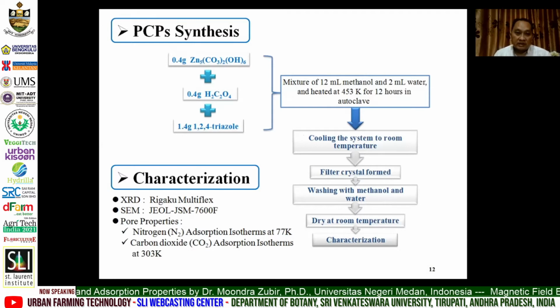This is the PCP synthesis stage. The zinc metal ion, oxalic acid, and triazole are mixed in 12 milliliters of methanol and 2 milliliters of water, and heated at 453 Kelvin for 12 hours in an autoclave system. After 12 hours, we cool the system to room temperature and then filter the crystals formed. For purification, we wash with methanol and water, and in the final stage dry at room temperature. We characterize this PCP by XRD, and observe pore properties by nitrogen adsorption isotherms at 77 Kelvin, and carbon dioxide adsorption isotherms at 303 Kelvin.